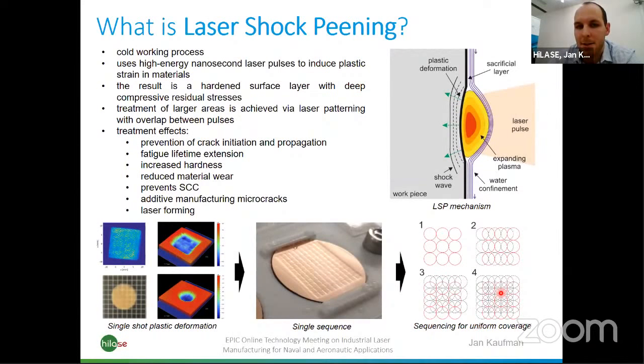Where is laser shock peening useful? Well, it's mostly in applications that are somewhat related to cracks, cracking and crack propagation. So mostly material fatigue, fatigue life extension. You can use it to prevent stress corrosion cracking, and also a new big area that is being opened right now is additive manufacturing, which we have already heard some questions about, which is associated with the micro cracks that are associated with the process.